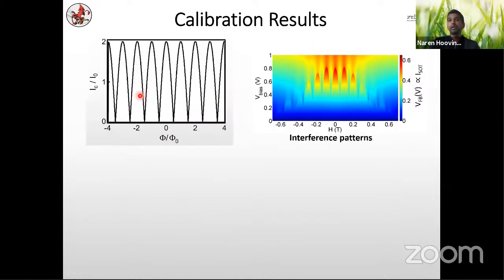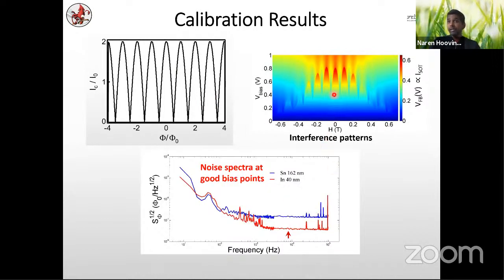And this must remind you of that oscillatory curve I showed you earlier. Basically, it is the same curve, and we need to choose points along this kind of map, and then bias the SQUID at that point. At that point, you would decide that the SQUID is most sensitive. So ideally, say something around here. If we bias the SQUID around here, then you would see that for small changes, you see a large change in the critical current, and that would then be translated into a voltage which we measure.